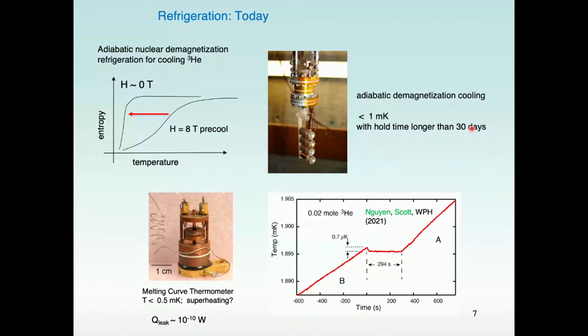But I did mention the melting curve thermometer earlier, and the validity of the melting curve thermometer is precisely this argument of the thermodynamic system, which is in play. And for a melting curve thermometer such as this one at Northwestern, I'm showing you the transition on warming from the superfluid B phase to the superfluid A phase. And there's clearly a latent heat here, which was measured in the early days. And if you use that latent heat together with the amount of helium-3 that's in the melting curve thermometer, you extract that the heat leak is 10 to the minus 10 watts. That is a tenth of a nanowatt.